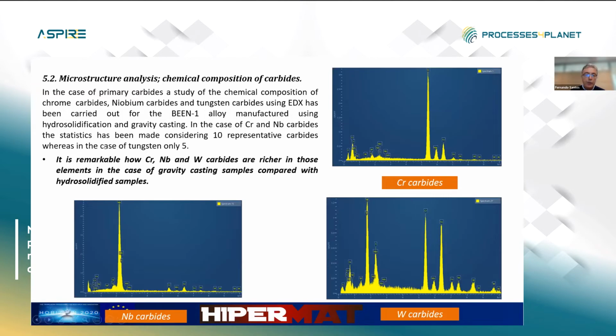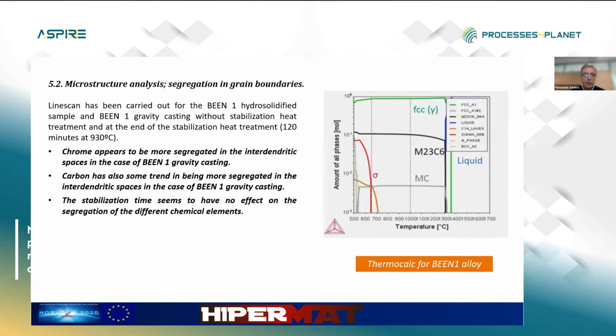The chemical composition of carbides is also slightly different. We have carbides richer in chromium, niobium, and tungsten in the case of gravity castings compared with hydrosolidified samples. This makes sense, since we have less segregation in the case of hydrosolidified samples.